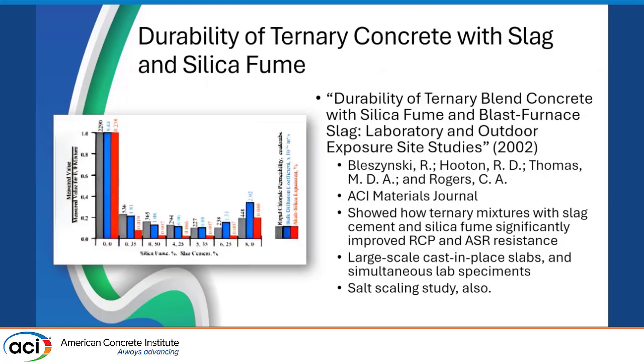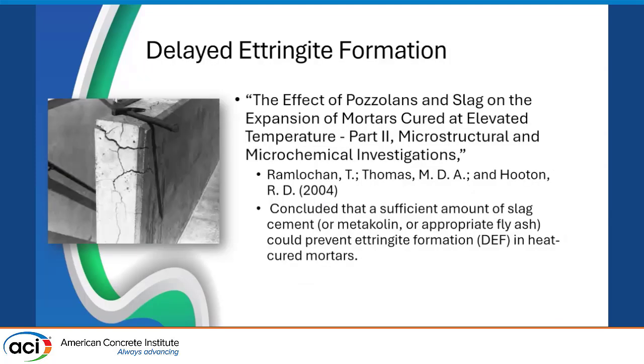Another paper is Durability of Ternary Blend Concrete with Silica Fume and Blast Furnace Slag. This was a series of laboratory and outdoor exposure site studies which showed how ternary mixtures with slag cement and silica fume significantly improved rapid chloride permeability and ASR resistance. It used large-scale cast-in-place slabs and simultaneous lab specimens, and actually looked at salt scaling too. We'll get into salt scaling a little more. Doug's done quite a bit of work on salt scaling.